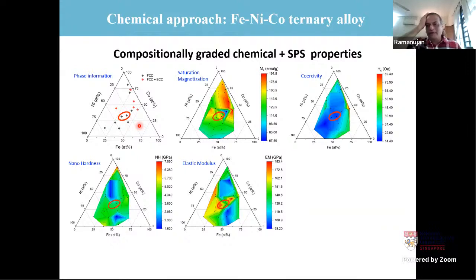Now, extending this to quaternary or other ternary systems, for example, going beyond classic transformer steels, which are typically Fe 3.5 silicon, people want to go to higher silicon, obviously, to increase the resistivity. So you have 6, 8, 10, but then what happens to the other properties? You cannot just focus on resistivity. And you can add other elements. Aluminum is just one example. The other thing is related to your Alnico question.